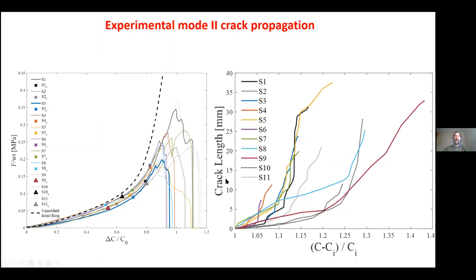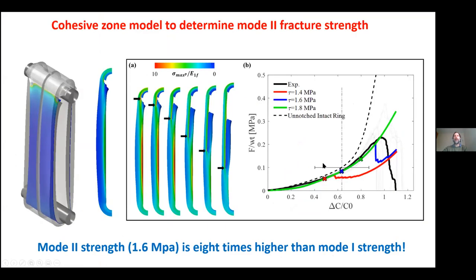And we were able to measure the crack length as a function of the strain energy that we're putting into the artery. And again, we got pretty good repeatability considering this is a biological material. And in order to calibrate, in order to figure out the shear strength of the artery, we basically had to perform this cohesive zone modeling. So this is our simulation of the experiment. And you can see that our simulation looks very much like the movie I just showed of the experiment. The crack is growing along the circumferential direction. So you can see it more clearly in these images here.